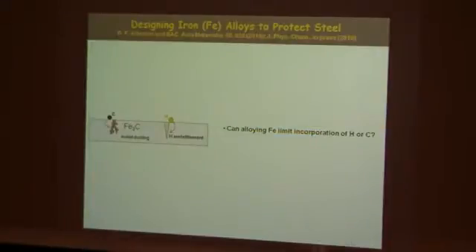And it turns out that suggestion didn't come out of thin air in terms of how we think you could potentially solve the problems that tungsten will face. It had to do with work that we completed recently, looking at how to protect steel from hydrogen and also steel from carbon incorporation. So steel is basically just iron, Fe, okay? And so we did a lot of work related to protecting steel, thinking about the energy and the rates of how fast carbon and hydrogen can get into steel, and they can cause all sorts of problems as shown here. Basically, you make compounds that can then decompose and just form all sorts of messes. And the hydrogen essentially, as I said, embrittles the steel and makes cracks.